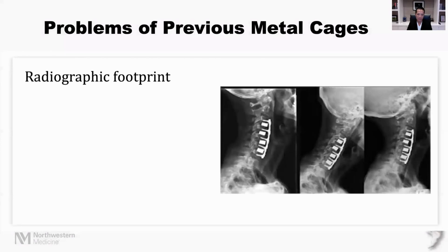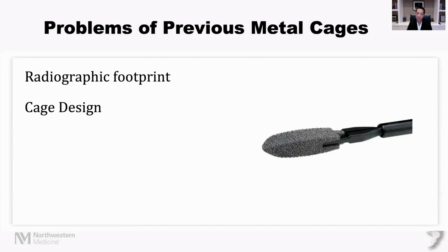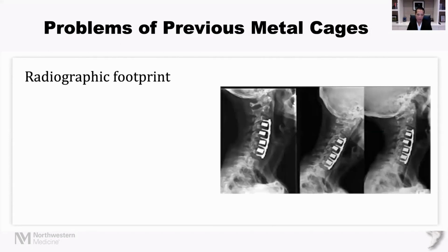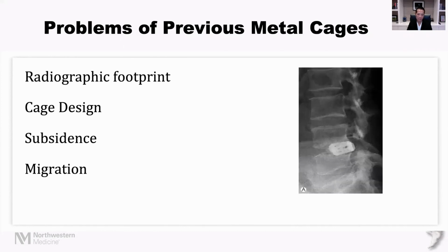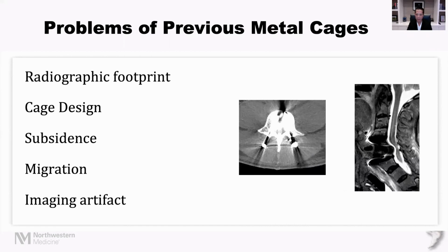The use of tantalum cages has created a number of problems and stereotypes against metal cages with its use in the past, including radiographic footprint and a design that precludes it from use in certain areas, such as areas that would require nerve root retraction or being close to the neural elements. Subsidence has been described with this cage, which then leads to cage migration. And then finally, imaging artifact is very challenging with the implantation of this cage and the need for imaging thereafter.